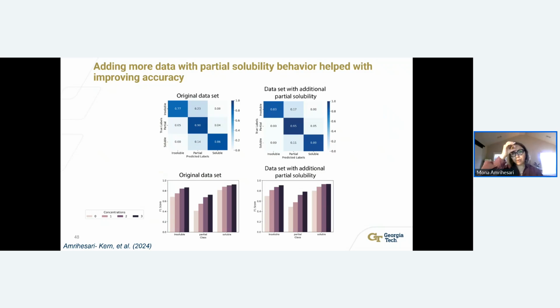So if you remember, I showed a slide on how the data was biased towards the two ends of 0 and 100%, and we had a little bit of data for the partial solubility cases, between 10 to 85. What we tested later is whether we could improve the model if we increased the data points. And this was what we observed.